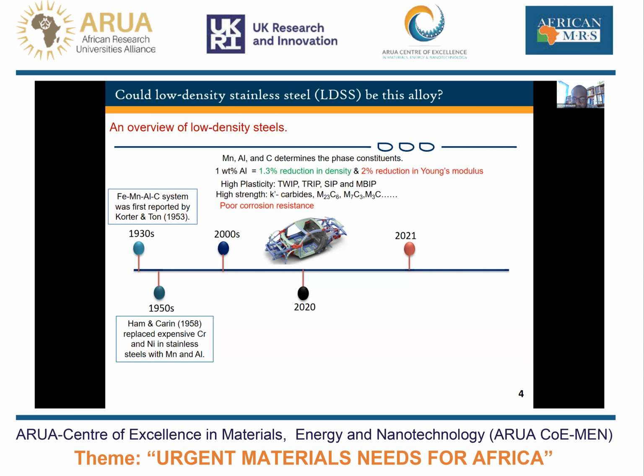As you can see, you can obtain a 1.3% reduction in density for 1 weight percent of aluminum that you add. But the disadvantage is that there's a 2% reduction in Young's modulus. And this is probably the reason why we don't have any low density steel still used in the automotive industry. But of course, adding a high amount of manganese and aluminum to iron and controlling the amounts of carbon could give you high plasticity and high strength.